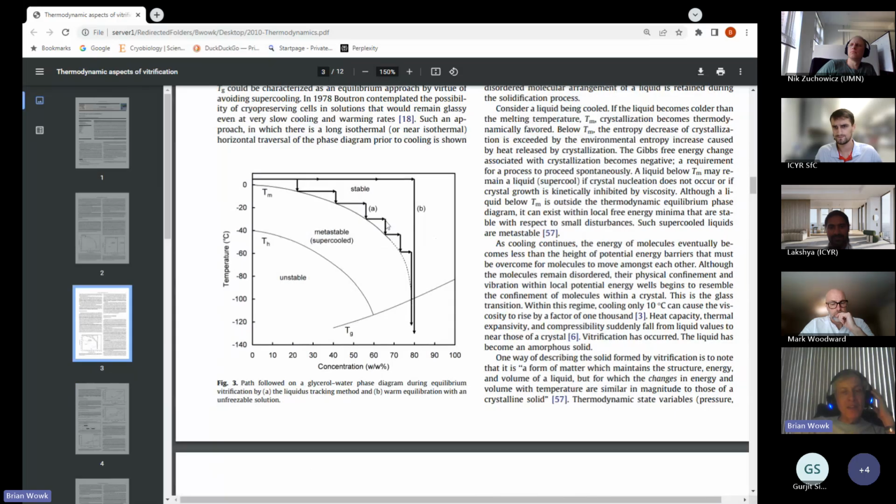So it's a technique for removing water from cells at low temperature that allows you to make the whole thing vitrifiable. And you're actually relying on whatever endogenous solutes are naturally present in the cells, plus the amount of CPA that you got in there in the early stages.